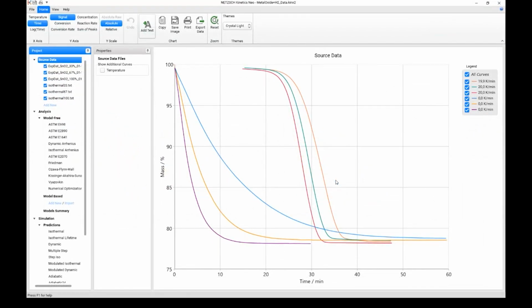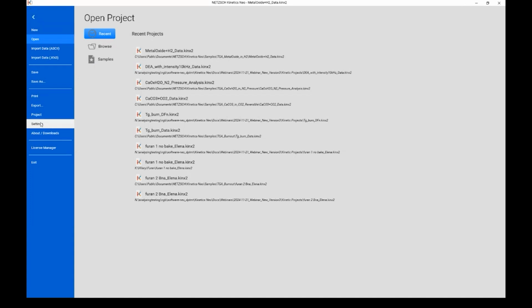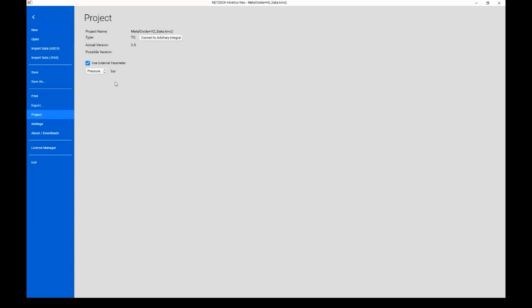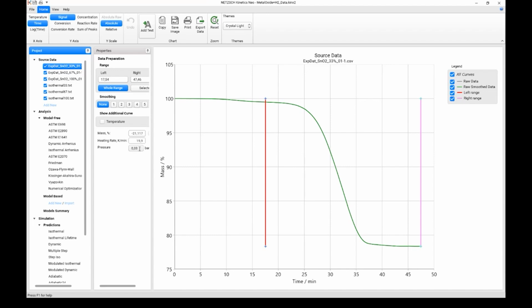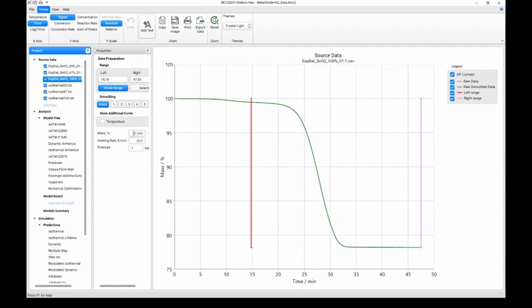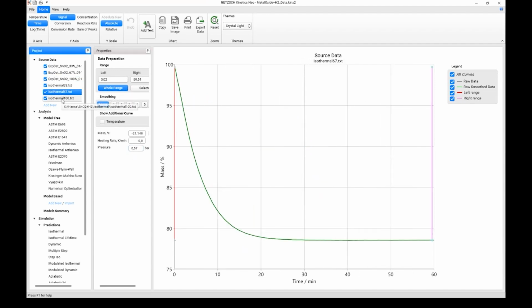Here we have all this data already loaded into the software, isothermal data and dynamic data. This project now has no dependence on the pressure of hydrogen and no influence of the pressure in the model. You see here, no model is present. Now let's go to the project. Then we select the external parameter, in this case pressure. Then we go back, and for each measured curve we must put a value of the pressure. For example, for 33% concentration we put 0.33 bar as the partial pressure of hydrogen for this measurement. For the next one it is 0.67. For pure hydrogen it is 1, and the same is done for isothermal data.